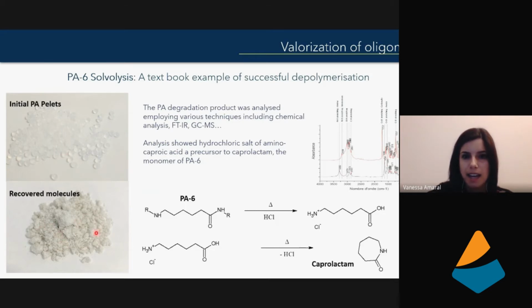We then analyze this white powder using different techniques. And what we show is that it's mainly a precursor of caprolactam. And caprolactam is a monomer of polyamide 6. So this caprolactam can be directly sold to the chemical industries to redo polyamide.